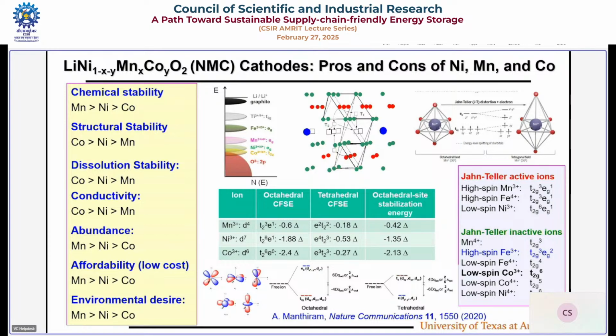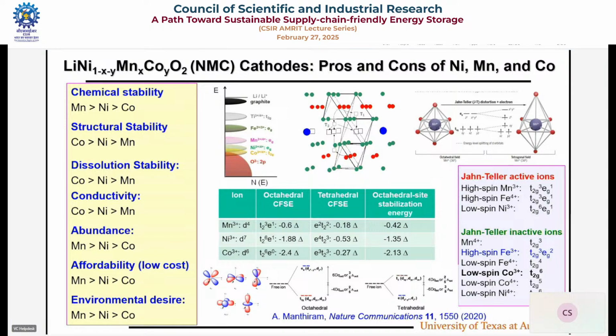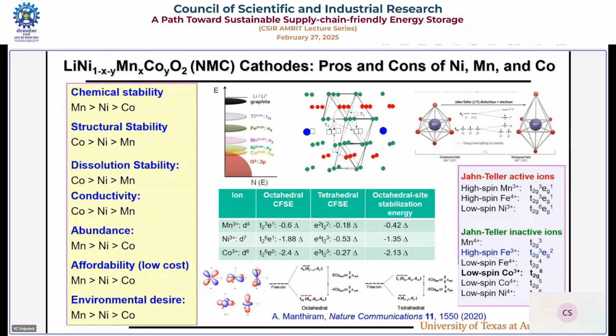Anytime you have that, these ions will tend to charge order, meaning 1 manganese will tend to go to 4+, therefore you won't have any electron here at all. The other one will become 2+, that means you will have 1 electron here, another electron here, no tendency to distort. Manganese 4+ will not have a tendency to distort to tetragonal geometry. Manganese 2+ will not have a tendency to distort. Manganese 3+, 1 electron, if it distorts, it will occupy a lower energy, so it will undergo. So I call it a charge ordering. Once it is, the manganese 2+ oxygen bond is more ionic compared to manganese 4+ oxygen bond. I can explain more if you need, but we don't have time, okay? Because it's more ionic, that oxygen is more basic, proton comes, trace amount of water present in the electrolyte, ppm levels of proton, attack, manganese dissolves. So that's the problem. So that also we can understand.